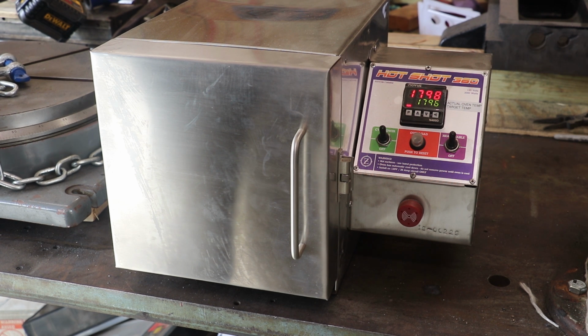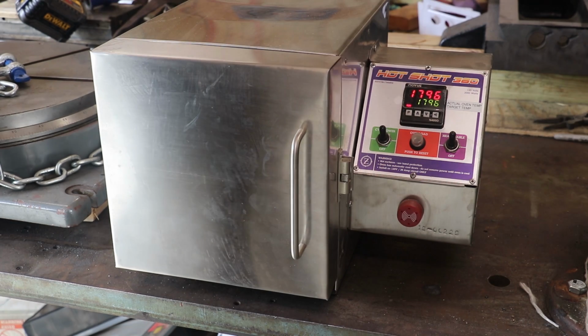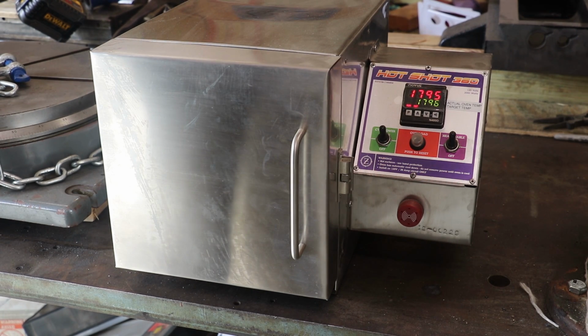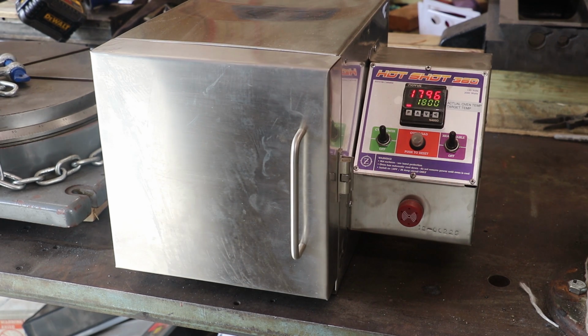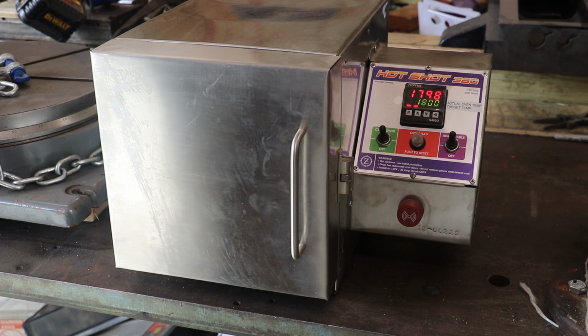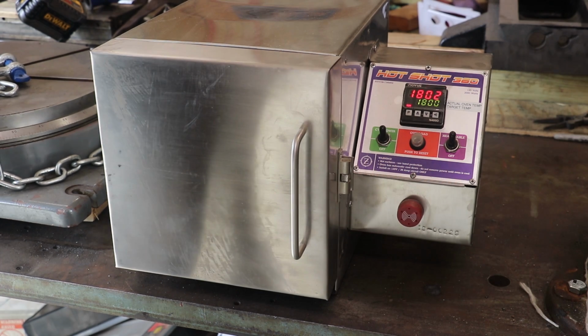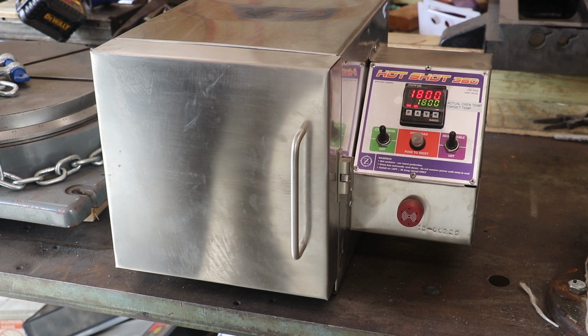So 1796 is where we're at. Our actual oven temperature will vary a little bit, but it stays pretty close to that. It's programmed to just cycle the heating coils inside on and off until we get there. Once we get to 1800 degrees, which we're there now, we're going to let that just sit there and soak at that temperature for, I think it's programmed for 30 minutes. According to the book, you want it to soak, I think, 20 minutes for every inch of thickness. We're only 3/8 inch thick there, so it won't take long to get that temperature all the way to the core of that piece of metal.